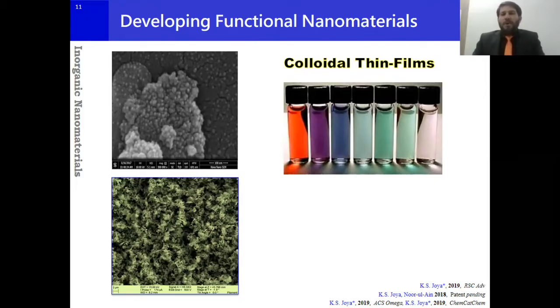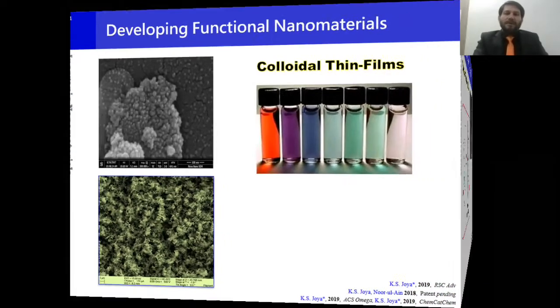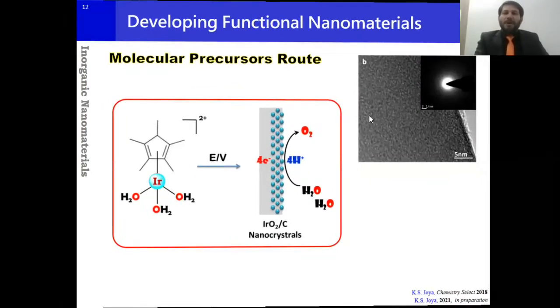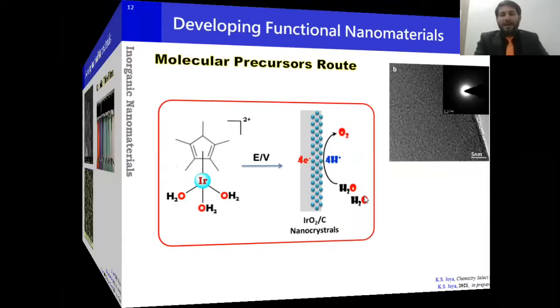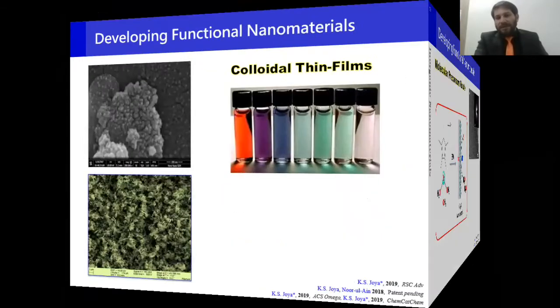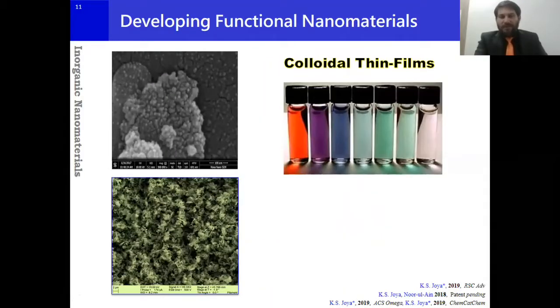So you can go roughly from 6.5 to 10, even in some cases to pH 11, 12, by using more carbonate instead of bicarbonate. So you can switch over the pH depending on whatever particle you want to make a colloid, and you can even control the size of the same colloidal nanoparticle by just shifting the pH up and down.